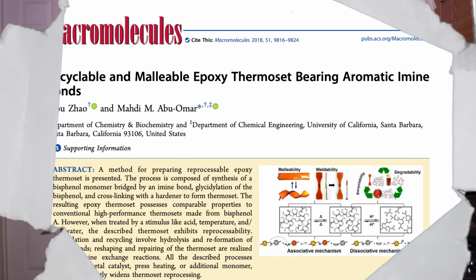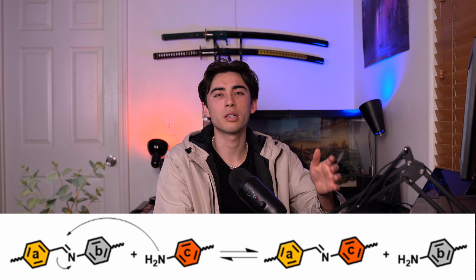The third system we are looking into for recycling are imine bonds, or C=N bonds. Imine bonds, commonly called Schiff bases, are often used for polymeric assemblies. This is primarily because imine dynamic bond exchange reactions occur under relatively mild conditions. Zhao and associates created a Schiff-base epoxy resin by embedding imine bonds into epoxy cross-link networks as intermolecular linkages. The resultant epoxy thermoset possesses good reprocessability and comparable properties to conventional high-performance thermosets. By acid-catalyzed hydrolysis of the imine linkages, reshaping and repairing of the thermoset are realized.